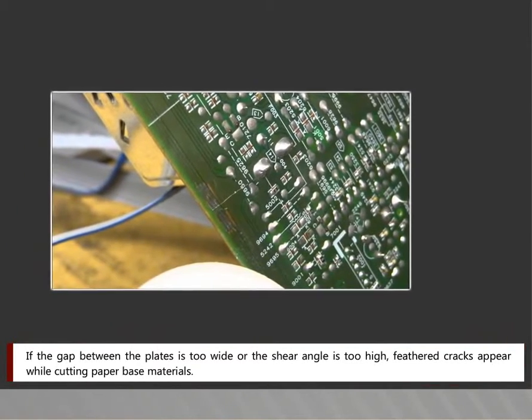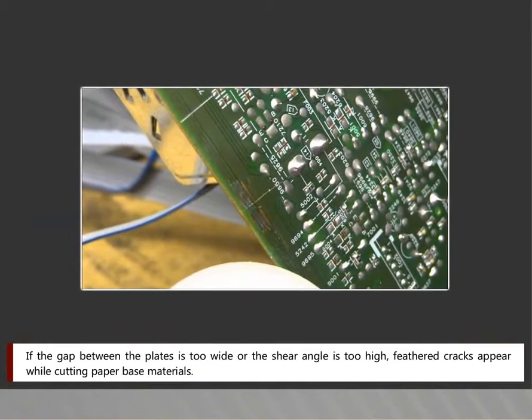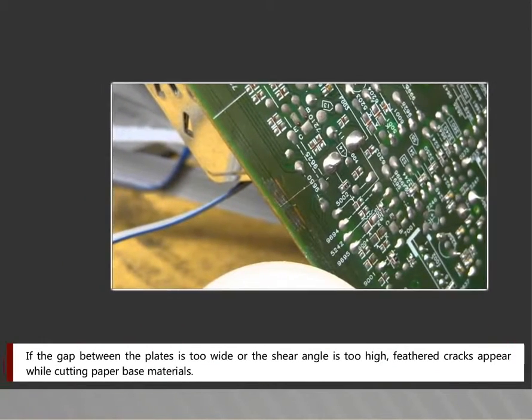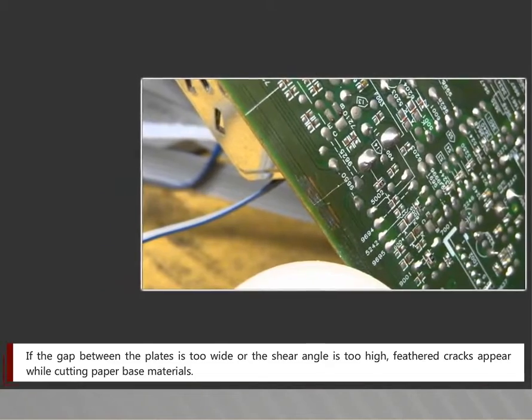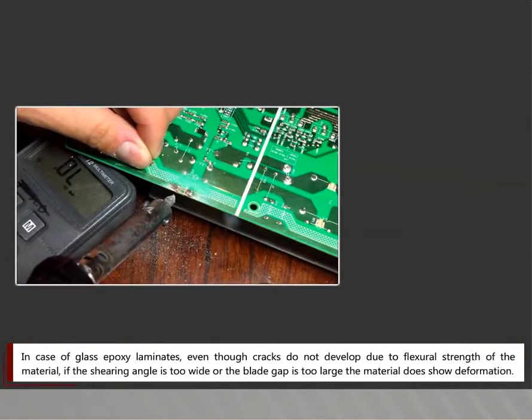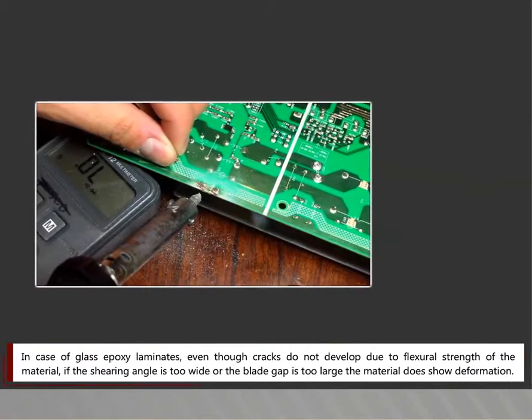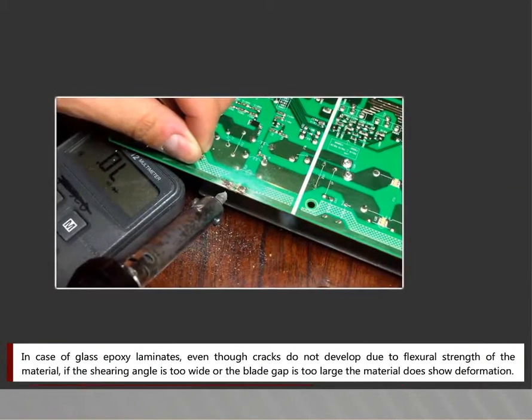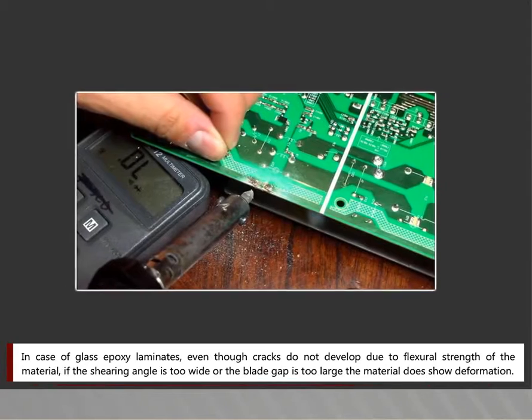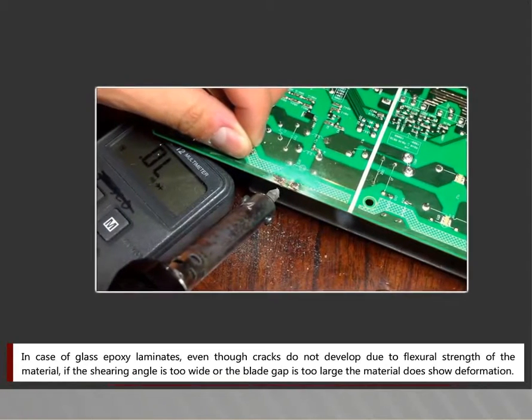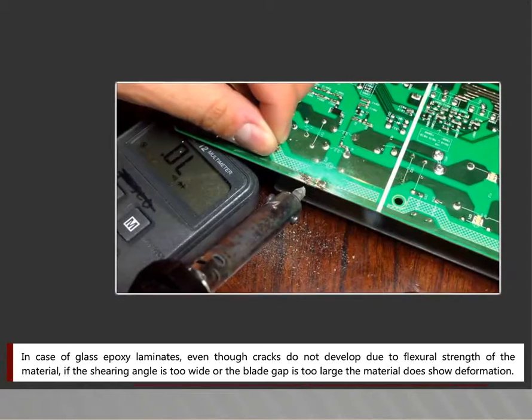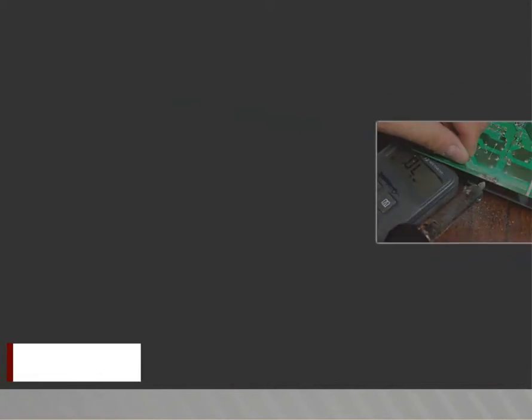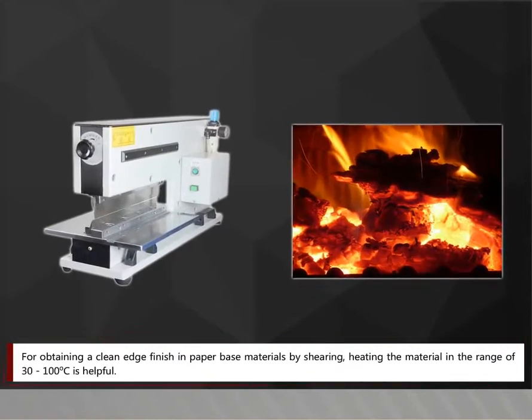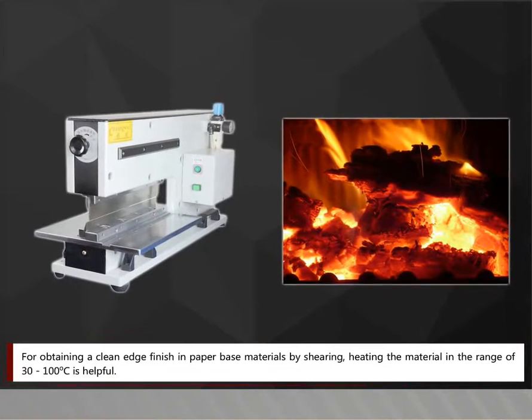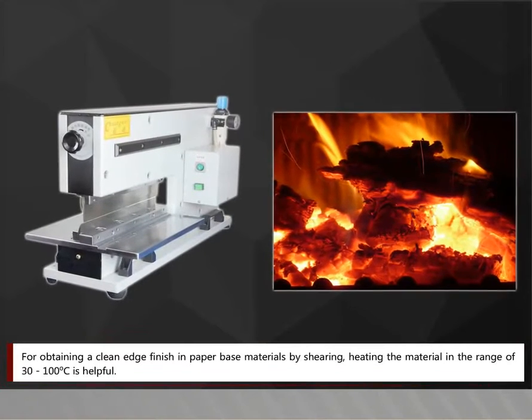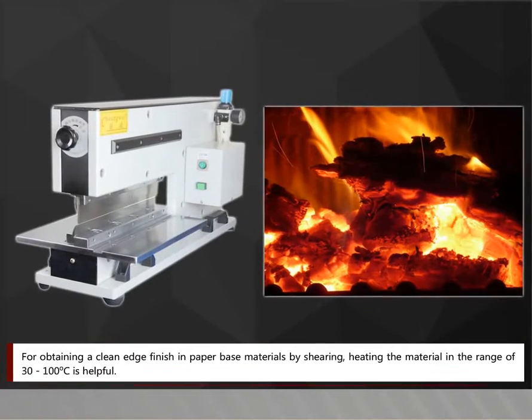If the gap between the plates is too wide or the shear angle is too high, feathered cracks appear while cutting paper-based materials. In case of glass epoxy laminates, even though cracks do not develop due to the flexural strength of the material, if the shearing angle is too wide or the blade gap is too large, the material does show deformation. For obtaining a clean edge finish in paper-based materials by shearing, heating the material in the range of 30 to 100 degrees Celsius is helpful.